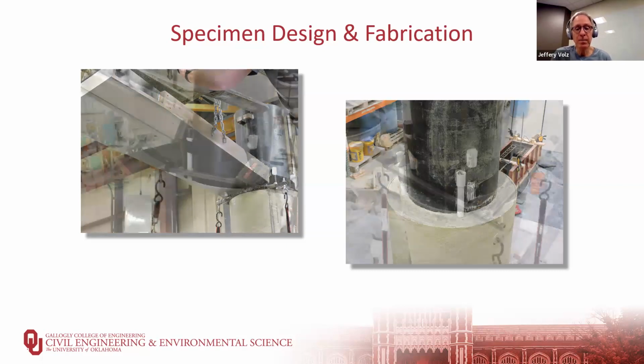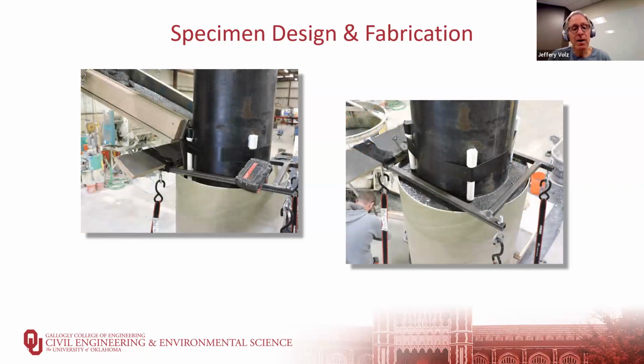And then here we have one of the FRP columns, our UHPC columns, placing that again with the same chute. It flows under its own weight. For those of you familiar with UHPC, it's a very unusual concrete. It only has cementitious materials and sand and an awful lot of high range water reducers. It's very flowable, but it's also very sticky. It tends to stick together. It's kind of like, I'm probably dating myself, but it's like Nickelodeon slime, except instead of being green, it's actually a dark gray, almost black. And it flows extremely well and fills up that 7 foot tall column with no external vibration and completely fills that annular space.